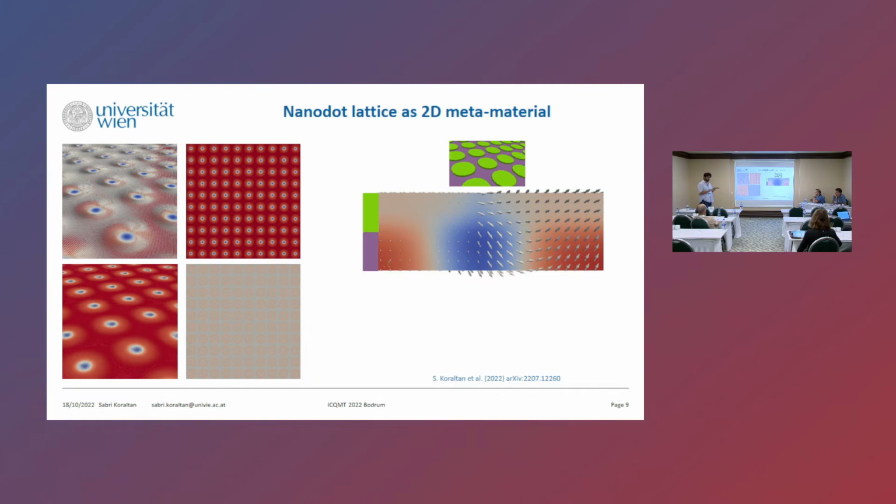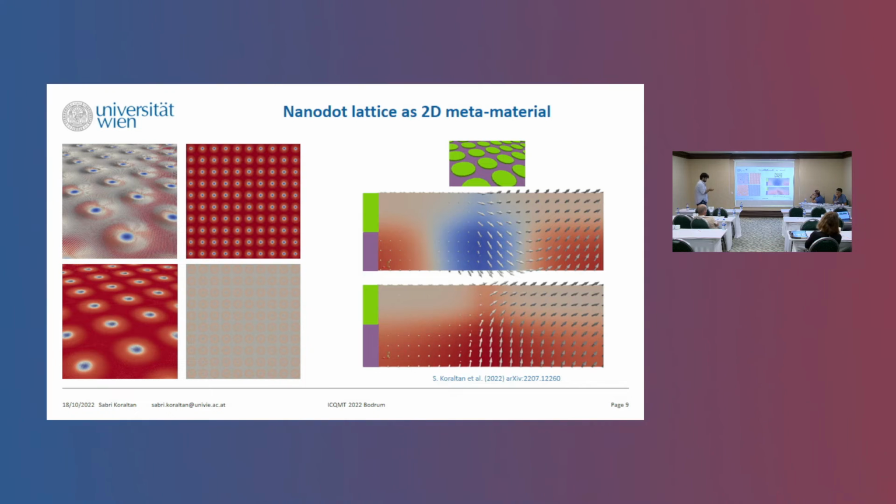This is not like the artificial skyrmion lattices that have been done previously, where you have some nanodot, and then you have a spacer layer which couples them ferromagnetically to the 1 or 2 nanometer skyrmionic layer underneath. But the dimensions are rather 30 nanometer of permalloy disk, and then 50 nanometer of a skyrmionic layer. And we can see here that it's fully diffused into the system.